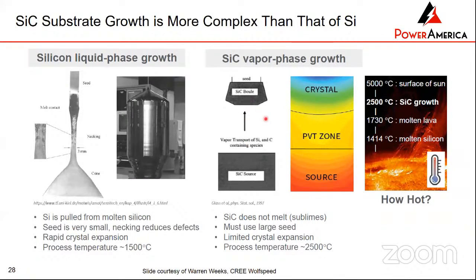So what I want to point out in this graph is when you make silicon carbide wafers, which is the starting material that you will take into the foundry to make devices, the process to make the wafer is more complex, and that translates to a higher cost. And also the way it's being made in silicon carbide, you start with a seed wafer, so that will allow defects from the seed wafer to propagate into the new wafers you're building.